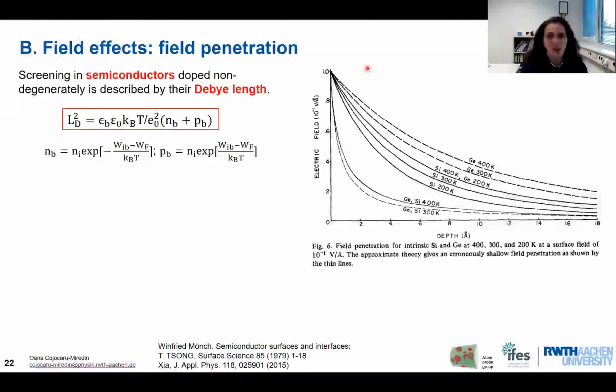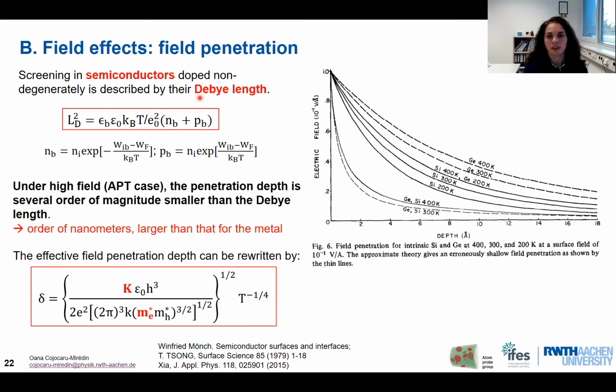And this also explains why we have mostly single ions and we don't have molecular ions on the mass spectra. So now if we go to the semiconductor and we speak about the field penetration depth, we represent this concept by the Debye length in general. But the problem, of course, is that the Debye length doesn't take into account the fact that we have a field applied on the tip. So another effective field penetration depth was developed by Tsong and co-workers, and the equation is given here below.